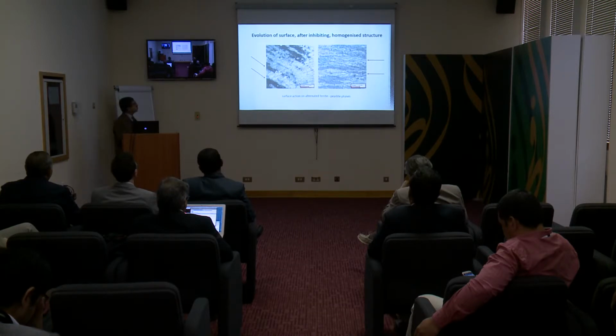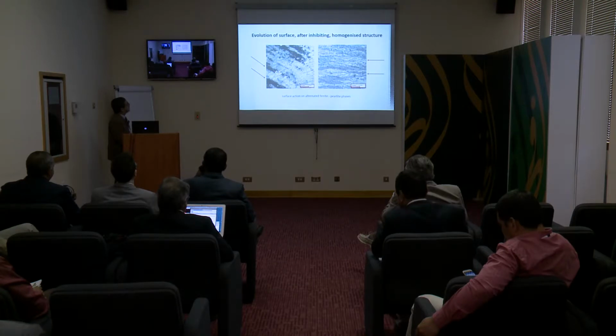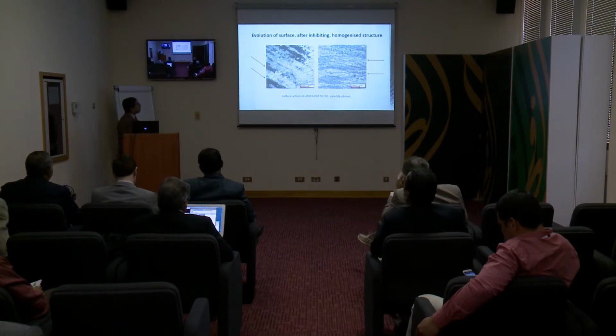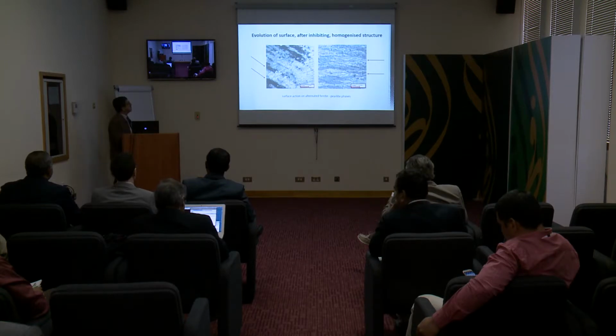When we try to make a link with the metallographic microstructure, here is the microstructure obtained by homogenizing at 950 degrees, and we obtain after 2 hours of treatment such a microstructure constituted of alternate bands of ferrite and pearlite. And when we look at the application of inhibitor, it follows the bands. That's because this inhibitor acts with some phases particularly.